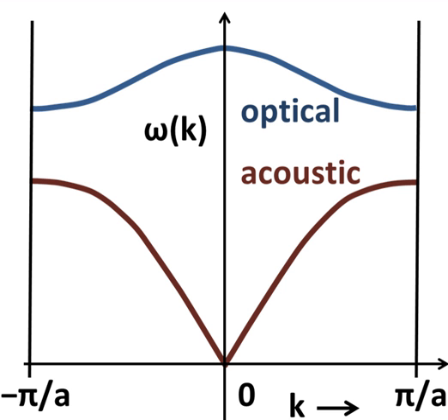Each normal coordinate Q_k represents an independent vibrational mode of the lattice with wave number k, which is known as a normal mode. The second equation for omega_k is known as the dispersion relation between the angular frequency and the wave number. In the continuum limit, a goes to 0, n goes to infinity, with na held fixed, u_n becomes phi(x), a scalar field, and omega_k is proportional to k. This amounts to free scalar classical field theory.